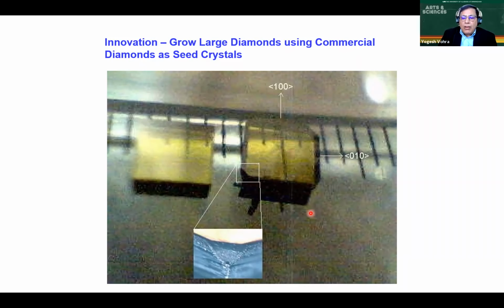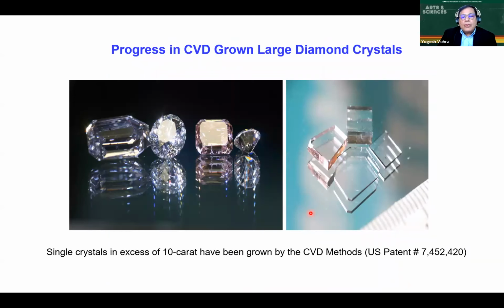So there's a lot of work that goes on in this field, but I want to just show you the results which have been obtained have been really remarkable. You can grow diamonds up to 10 carat using this process. And those single crystal diamonds have actually been used in some of the high pressure experiments which I described. You can also, with this method, by controlling impurities, grow commercial white, very ultra pure diamond using this technique.